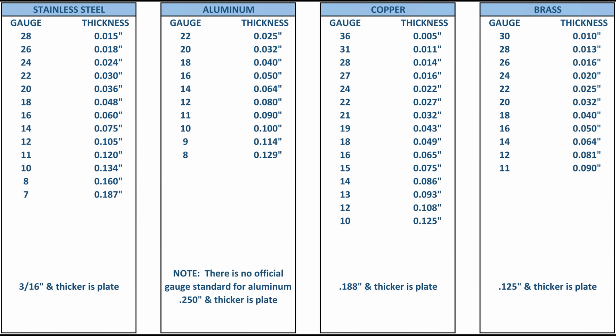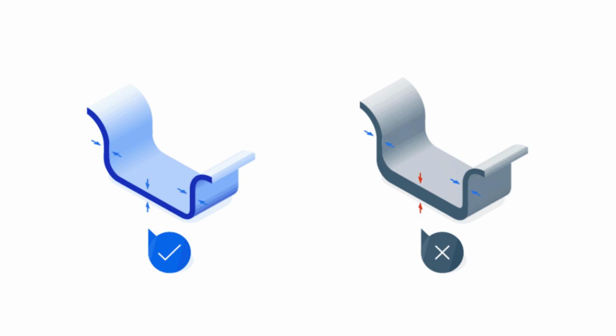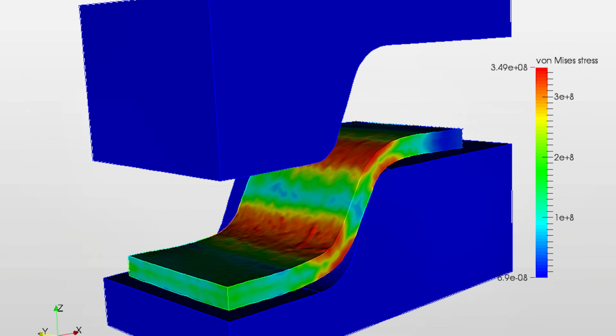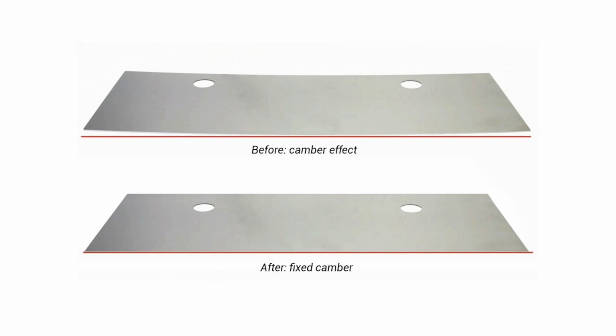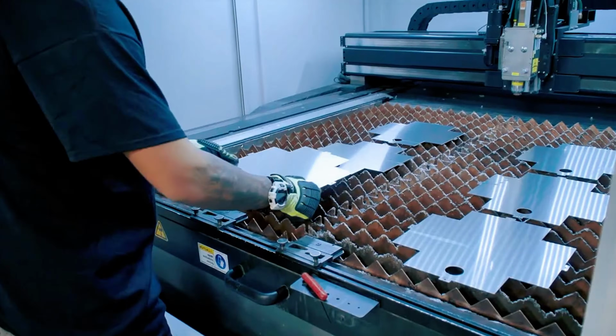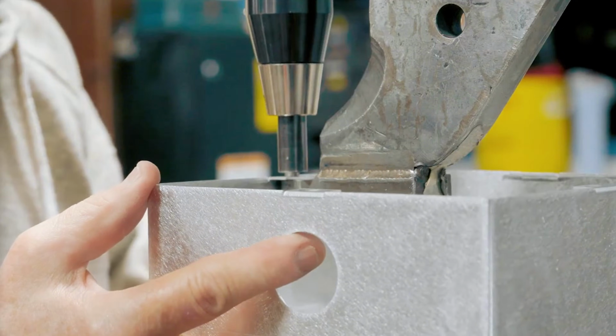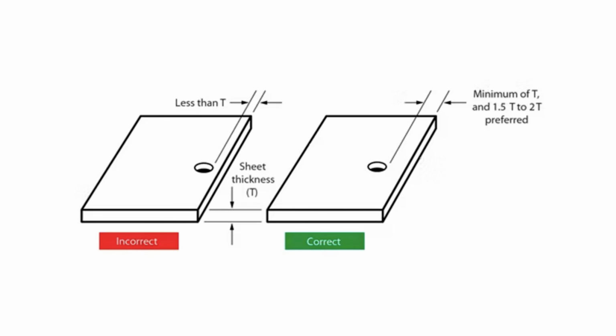Spring back depends on many variables but can be predicted with reasonable accuracy using K-factors, spring back factors, elastic modulus, and yield strength. Based on my experience, mechanical engineers can design sheet metal parts with appropriate compensation for spring back. The manufacturer's expertise will then fine-tune the process to meet your specifications. Next is material thickness. Thicker sheets are stronger but harder to form, and thinner sheets can be shaped more easily but lack strength. You should also avoid drastic changes in material thickness that can lead to stress concentrations and defects such as cambering. The fourth constraint is hole placement. Sheet metal is prone to tearing or distorting when there are holes, so keep them at least 2 to 3 times the material thickness away from the edge of the sheet.